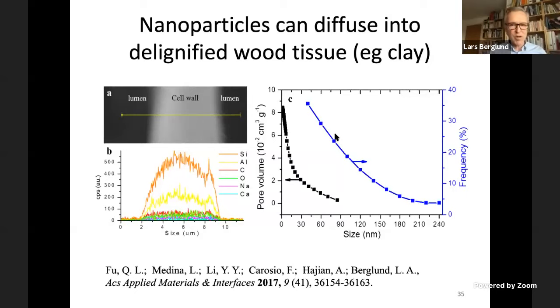We know from earlier work that we can diffuse nanoparticles from colloidal suspension into the wood tissue. This is clay. So this is the lumen, this is the cell wall, and these are EDX data showing that we have silicon inside the cell wall. And the reason, of course, is that the size of the porosity in delignified wood is perhaps 90 nanometers, and some of the clay nanoplatelets are small enough to diffuse into that space.